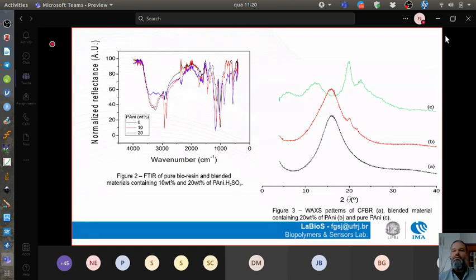Here we have some results. In the left corner, we have the FTIR. This spectra show us the PANI characteristic bands, while in the right corner of this slide, we are seeing the wide-angle X-ray scattering, which is more useful to us in this case because, as we can see here, we have the cardanol furfural and the blends with different amounts of PANI. In this case, 20% of PANI, and here the PANI. Okay, so looking at this result, we can understand that in this blended material, there is a kind of phase which is from the PANI.